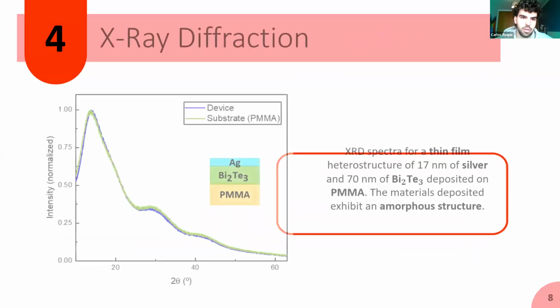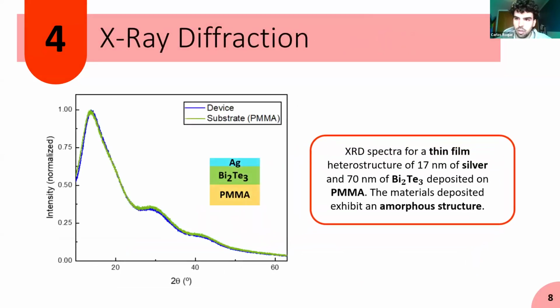And then we measured by X-ray diffraction our samples, not the grating ones because we cannot measure those under X-ray diffraction, but the thin film. We use PMMA as a substrate, as I already told you. Then we use bismuth telluride as the topological insulator material. And then we deposited a silver layer on top of that because it's easier to excite plasmon modes on silver. And then we can couple the plasmon from the silver to the bismuth telluride and take advantage of the properties of the topological insulator material. As you can see in the X-ray diffraction spectrum, we don't have any peaks. We identify an amorphous structure, and we think that's because PMMA is also an amorphous substrate.